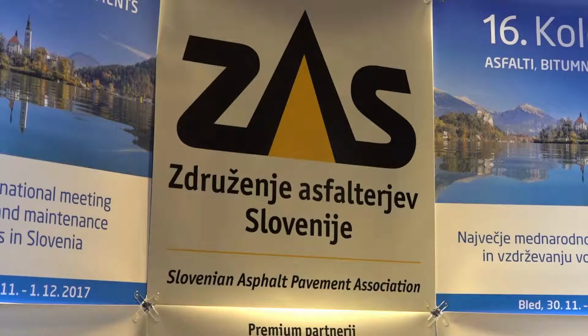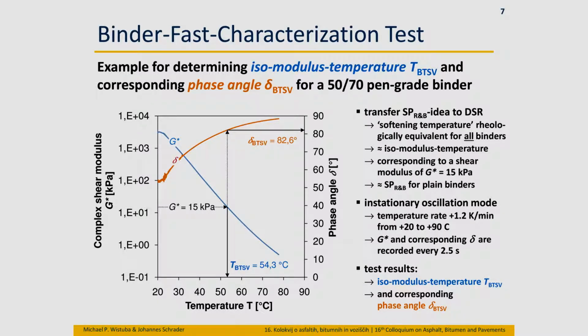You find an equi-stiffness temperature, or as we call it right now, the isomodulus temperature. The idea is a softening point, which is an equivalent rheological parameter for all binders. As you can see on the graph, it's an instationary testing mode, which means that temperature is increased during the test by a constant rate of 1.2 Celsius per minute, starting from 20 to 90 degrees. Then you measure G star, which is decreasing at the same time, of course, because the binder gets softer. So you see the familiarity with the softening point method. At the same time, the phase angle is increasing.